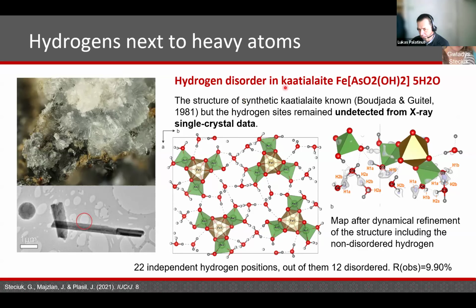This is another mineral. It has a very tongue-twisterish name, kaatialaite. It's iron arsenate, and it contains a lot of water and OH groups. And it turns out that the structure contains a lot of hydrogens, 22 independent positions, out of them 12 are disordered. So all these half-colored, half-shaded positions are only half-occupied hydrogens. And it was possible to determine the structure completely, including all these partly occupied hydrogens, with dynamical refinement from electron diffraction data, and it was not seen at all in the X-ray diffraction data.